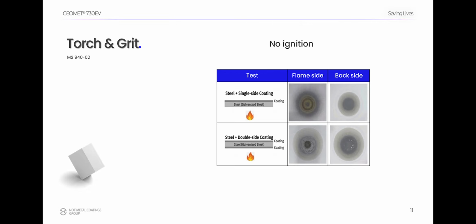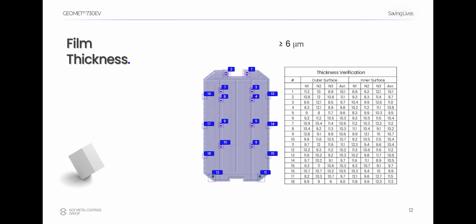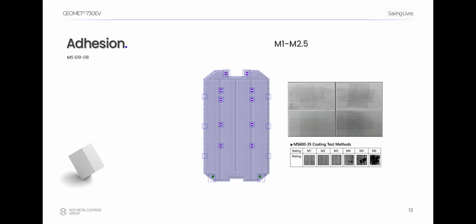Now let's briefly look at each test result. These results were verified by Hyundai Motor Company. In the torch and grit test, there was no ignition on both the flame side and the back side. For film thickness, GeoMet 730EV achieved more than 6 micrometers in all measured areas. For adhesion, it met the crosshatch requirement even on GA steel. This is important because GA steel can be a difficult substrate for zinc flake coatings.